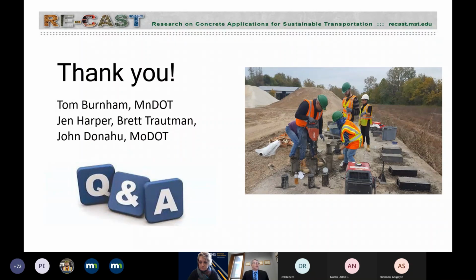We were involved and wrote 2 big reports as part of the ReCAST project on RCC technology. And the earlier slide that I showed, on packing density and its effect on properties, was all done with the objective of how to better design durable RCC pavements. So for the RCC, in both case studies, it was from the experience of the contractor that they proposed this mixture proportion. The only thing that we intervened in the second mixture is we'd like to test the fibers, and then we worked on trying to optimize the consistency and the properties that would tell us: is it 4 pounds, 5 pounds, or 6 pounds per cubic yard of fibers.